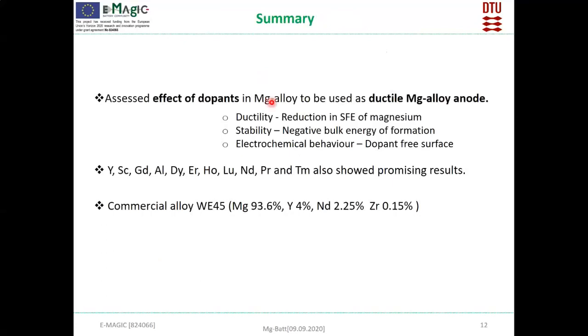To summarize, in my work, I assessed the effect of dopants in magnesium alloy to use as a ductile magnesium alloy based on 3 criteria. The first criterion is to check whether it is ductile. For the ductility, I checked based on the reduction in the stacking fault energy of magnesium. Then I looked at the stability of these alloys. For stability, the bulk energy of formation should be negative. And we identified that out of the 33 elements we studied, 20 elements are stable with magnesium to form an alloy.